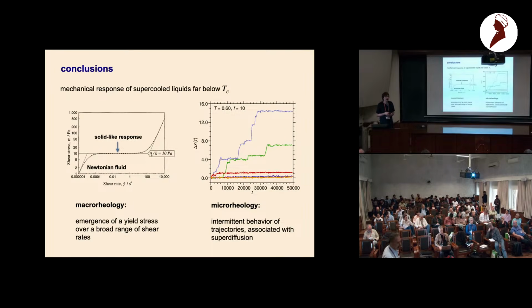This is your statement? Okay, but this is only the linear response. Okay, but this is a bit mysterious because we know that without shear, the relaxation time of swap type dynamics is significantly faster than standard MD. Right. At the same time, we know that the viscosity and the relaxation time are more or less proportional to each other. So this means I would expect your flow curve to be sort of an effective flow curve giving rise to much smaller viscosity at the small shear rate regime, instead of having exactly the same value as standard MD.